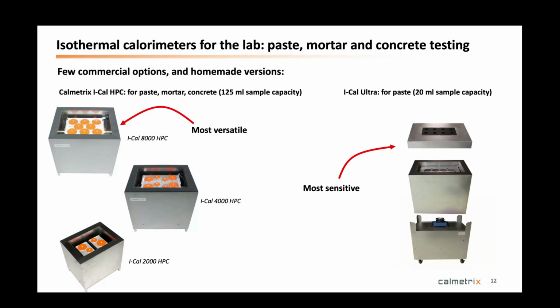Some tests are trickier because you have a little bit more sample size or less sensitivity. Like typically the ASTM C1679 is trickier. It takes more time to actually learn how to do it. But eventually, with the apparatus that you have on the left, you can do everything. On the right-hand side, you would have the iCal Ultra, and that's more sensitive, but it's really limited to paste. So things like admixture development and robustness testing or admixture formulation, or even sulfate optimization, are iffy because they should be done in mortar. There's a strong point to be made that cement paste is not good enough or very often can be misleading. So you have a choice between one or the other.